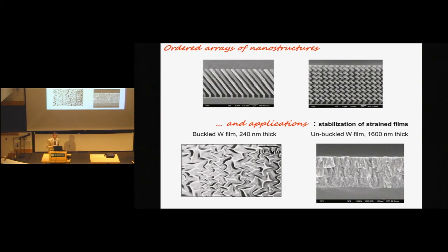Now, let's talk about thin films. Growing thin films is something very common in the microelectronics industry, right? But growing metallic thin films actually poses a big problem because stresses develop as the thickness increases, okay? These are both thermal stresses, but also growth stresses. That is, it's an intrinsic phenomenon you cannot really get rid of as you grow the film. If the energy stored in this growing film becomes large enough, the energy is going to be released by some mechanism, and usually what happens is the film buckles off. So you end up with something like this.